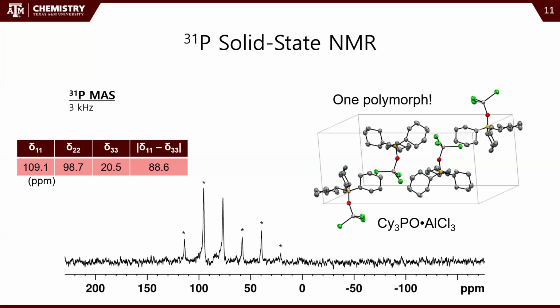Also, we only have one isotropic peak, and so that tells us something about the crystal packing, because the isotropic peak depends on the crystal. So if you have, for example, 4 different molecules in the unit cell, you can have up to 4 peaks if you only have the one polymorph. But all of these phosphorus nuclei are in very similar environments, and so with the resolution of the spectrometer, we only see 1 peak.